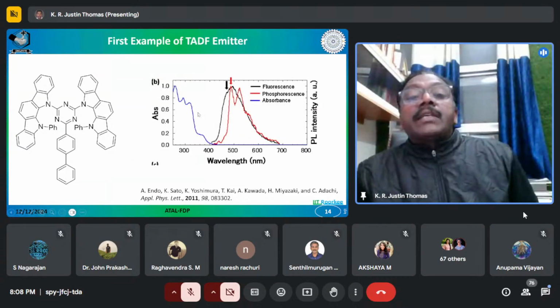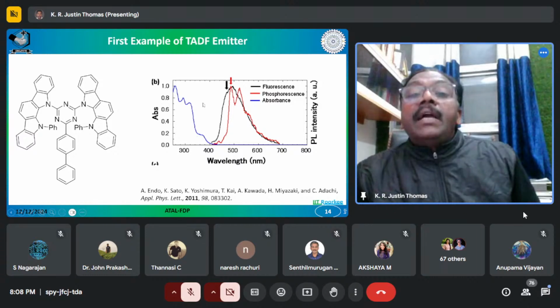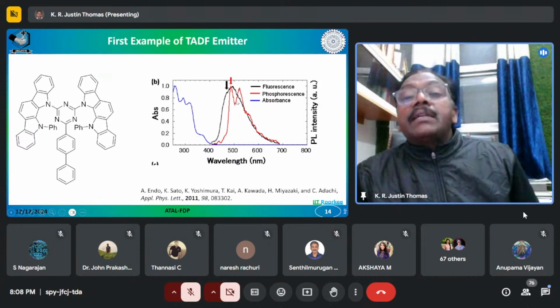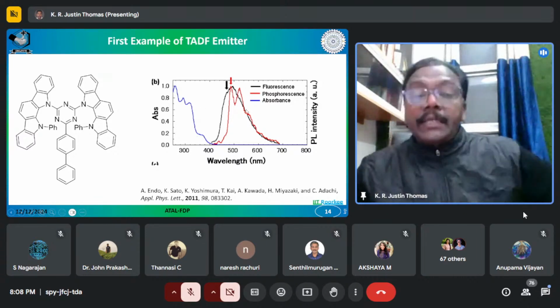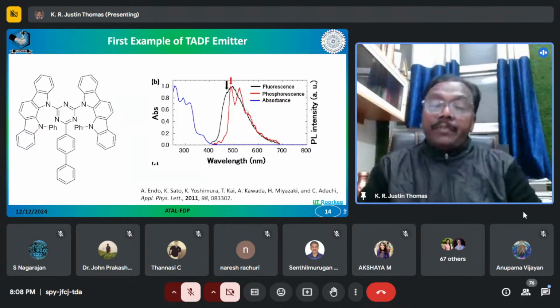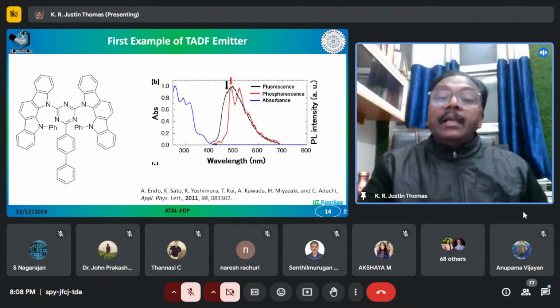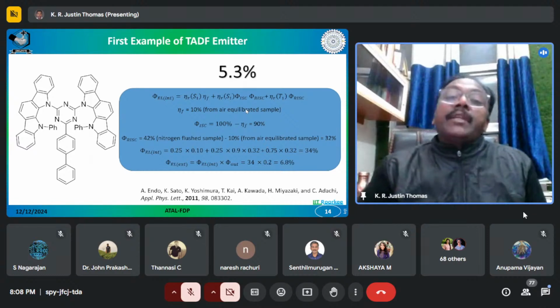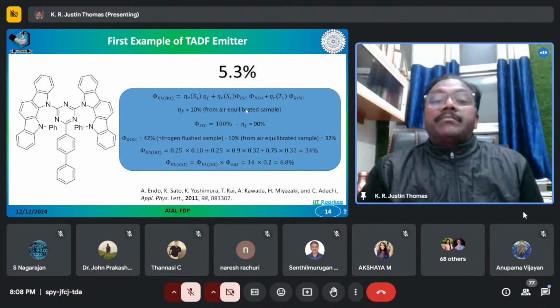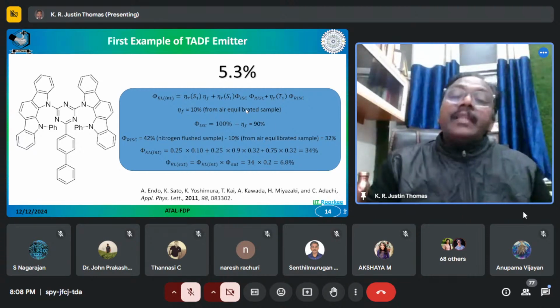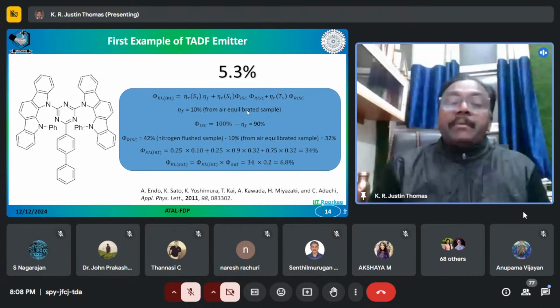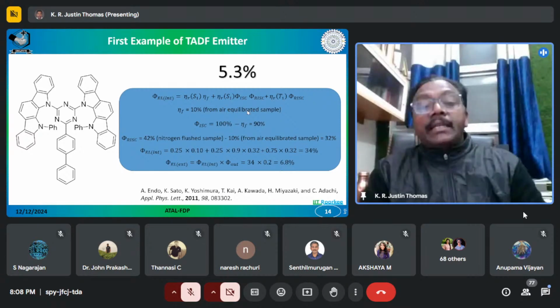And this molecule has an absorption. There is no charge transfer absorption because HOMO and LUMO are well separated, and the fluorescence and phosphorescence almost overlap. That indicates that the delta EST is very small. And finally, it showed an efficiency of 5.3%, which is higher than the theoretically permitted one. So this was in 2011.